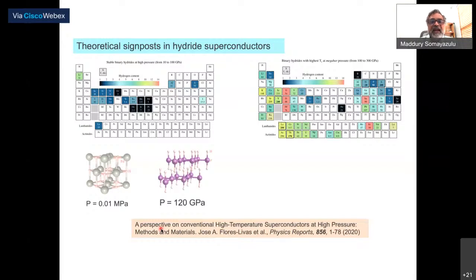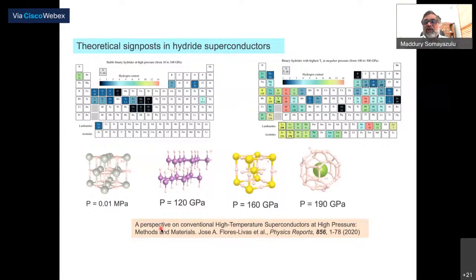You go to about 120 GPa, you have phosphorus hydride, which has two hydrogens per phosphorus in an arrangement which is having a higher transition temperature, but still you only have a very small amount of hydrogens per metal. On the other hand, sulfur hydride H3S, which superconducts at a whopping 203 Kelvin at 160 GPa, has a clathrate-like cage of hydrogens surrounding sulfur. And obviously, this is the structural motif, which is possibly contributing to higher transition temperature. Go to lanthanum hydride, which we worked on and showed that the transition temperature is as high as 265 Kelvin. You find the structural motif has changed. You have a larger number of hydrogens sitting around the lanthanum.